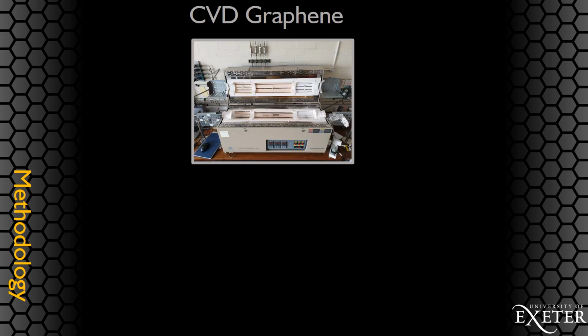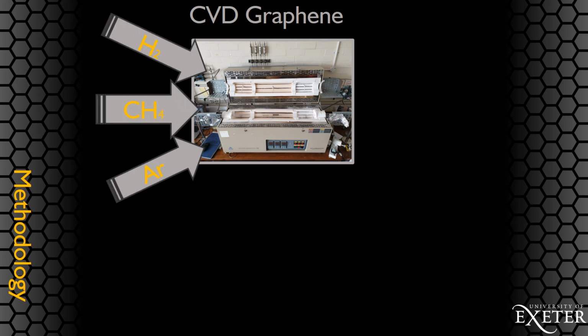The CVD graphene was made in a low-pressure, high-temperature quartz oven. Methane acts as the gaseous source of carbon, argon gas purges the chamber of contaminants, and hydrogen aids the carbon deposition. A copper sheet is inserted in the oven and brought up to a high enough temperature to cause carbon to deposit on both sides of the copper.